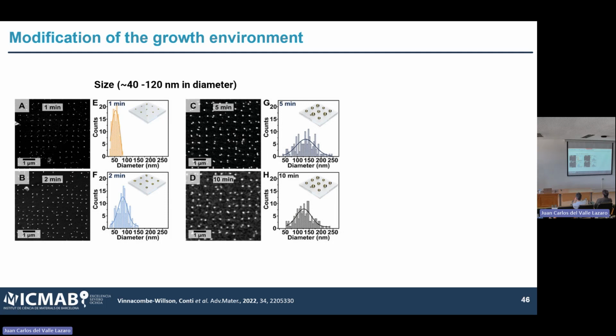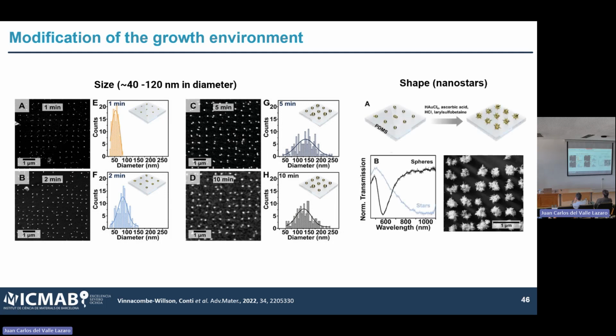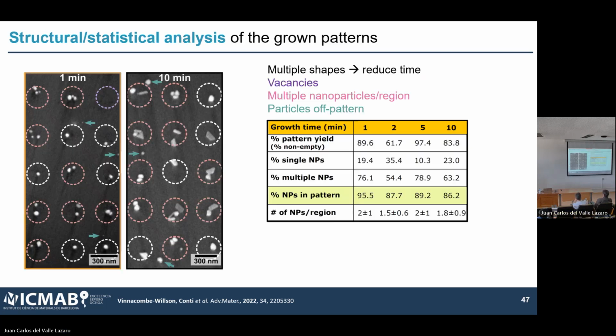Which starts to be very interesting because when you get down to very small particles, we were able to show that we could modify them. So we did a second growth step on the very same substrate and went, in this case, from spheres to stars. So again, this is promising in our vision in order to start to apply all the growth that we know how to do in solution on the substrate.